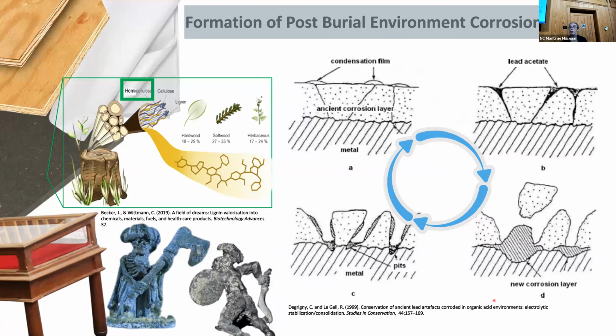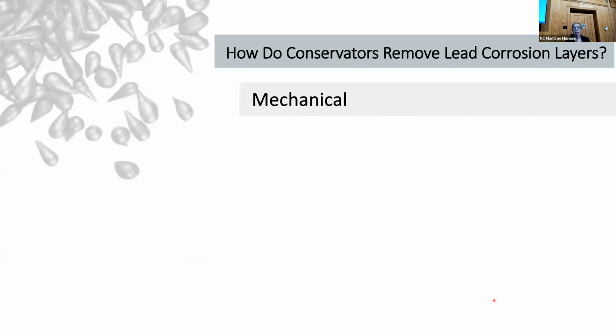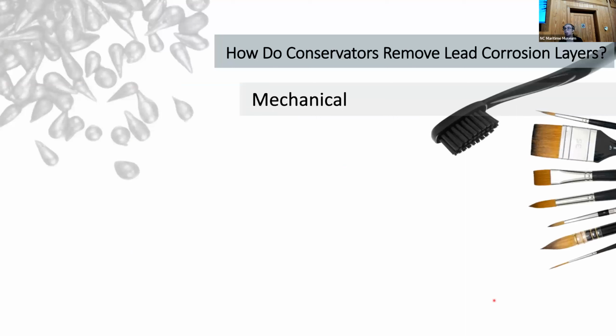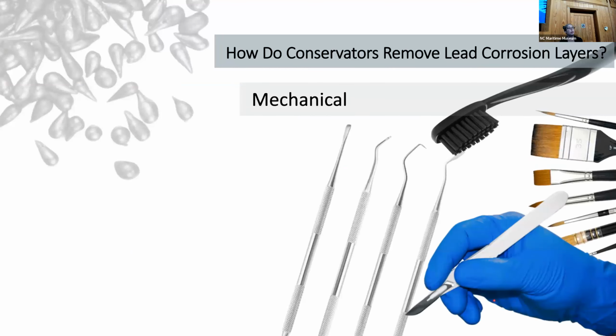Most conservation treatment for lead either involves cleaning the surface so we can see what it looks like, or cleaning the surface in order to stabilize it, to try to remove any type of corrosion products that might contain these organic acids, so this doesn't happen, essentially. So how do we do this? Well, we can do it mechanically. How we do it mechanically, obviously, we can start very gently with brushes. We can then move on to hand tools like scalpels and dental picks and things of that nature.